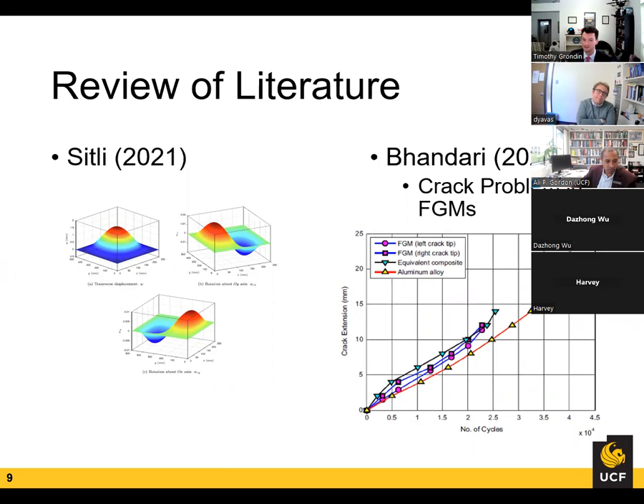And then in 2022, Bhandari specifically addressed an issue that was common to functionally graded materials that have been produced in the past. He specifically addressed crack tip stress fields, dynamic stress intensity factors, and crack growth throughout these materials. Cyclic mechanical loading, cyclic thermal loading, as well as impact loading were all addressed. And it was found that the cracked functionally graded plates actually exhibited a higher fatigue life when compared to that of their equivalent composite plates when subject to the same loading and boundary conditions.